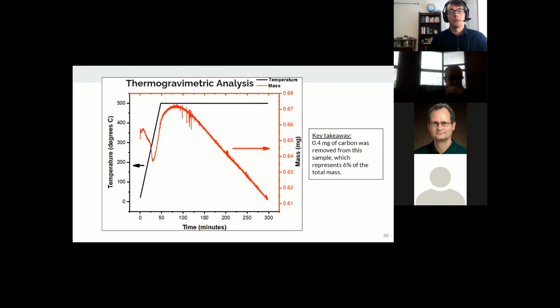To remove the excess surface carbon, several methods could be employed. The two most common methods are acid-based removal and thermal oxidation. The acid-based removal route requires the use of concentrated nitric acid, which is a dangerous oxidizer if you're familiar with it. Due to this, thermally oxidizing the carbon away was our preferred method. We used a thermogravimetric analyzer, or TGA for short, to controllably oxidize the carbon at a constant temperature. Using the TGA also gives a quantitative measurement for how much carbon was removed from the powder. One sample, which had about 6% excess carbon, is pictured here, was kept in the TGA for 5 hours at 500 degrees Celsius to bake off the carbon.